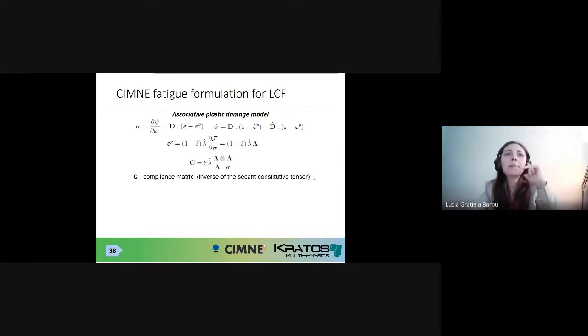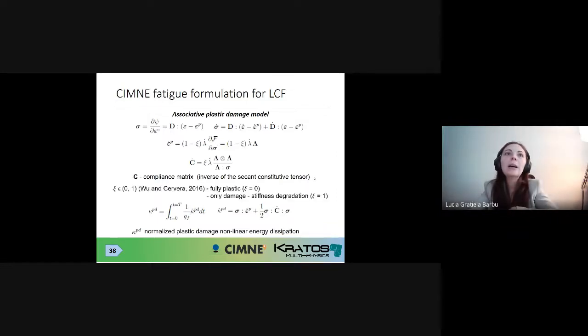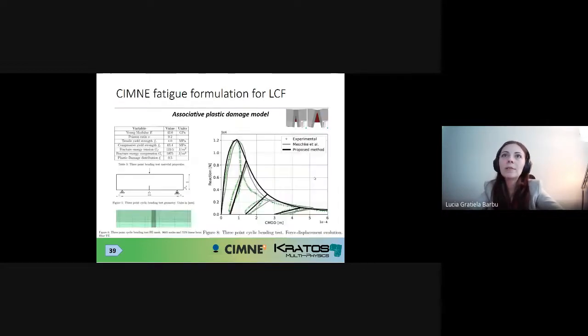The associative plastic damage model. We have a compliance matrix over here. As I said, the dissipation variable is unique, normalized plastic damage dissipation. And this is based on a Xi parameter, which varies between 0 and 1, as proposed by Professor Wu and Cervera. 0, fully plastic behavior, 1, only damage stiffness degradation.